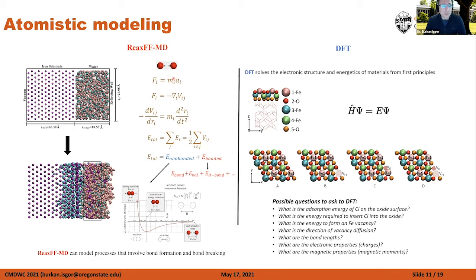Reactive force field molecular dynamics is basically a simple, well, theoretically simple approach where you assume that the atoms interact with each other following Newton's second law. You have to define an acceleration based on a force field, and that force field has to be defined in different ways. You have to define some non-bonded energies and bonded energies. And with this approach, with molecular dynamics, you can model processes that involve bond formation and bond breaking, which are very relevant to the chloride-induced depassivation.